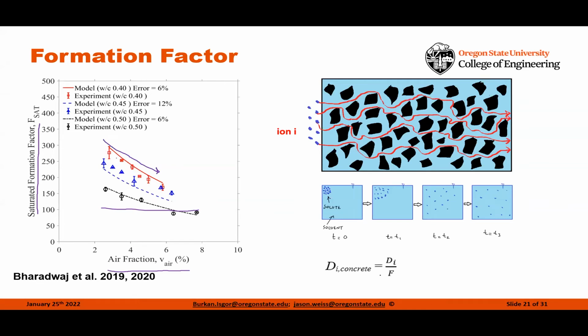Now that we have the formation factor, we're able to actually use the formation factor along with the ionic diffusivity of the different ions to start to predict the diffusion coefficients of the ionic species in our concrete. So now we're able to start to bring this in with reactive transport models and start scaling this up.